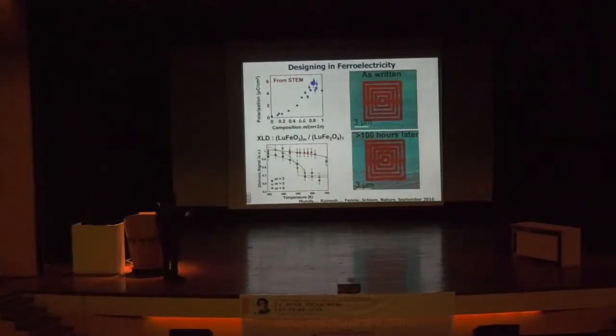So we can also go back and design in the ferroelectricity, but that wasn't that big a deal because the parent compound was already a good ferroelectric. And we have done a lot of measurements using dichroism, and indeed we can tune the ferroelectric transition by using various layering sequences. But here's the most interesting measurement that we did, not in this picture, in the next slide. We can write ferroelectric patterns. The reds and the blues are simply polarization vectors pointing up and down. They're very stable over months now. This was done almost a year ago.